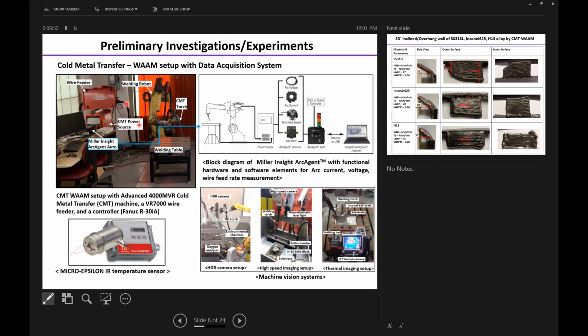So for this we use this setup, the cold metal transfer based WAM system. It consists of a wire feeder, CMT power source, and the welding robot, which is controlled by a robot controller. Then the welding table on which the welding substrate is mounted, then the Miller Insight Arc Agent that is used for acquiring data such as arc current, arc voltage, and wire feed rate. Then we also have an IR pyrometer used for measuring the temperature, and a machine vision system to record videos during the deposition process. We have an HDR camera, a high speed imaging setup, and a thermal imaging setup also.